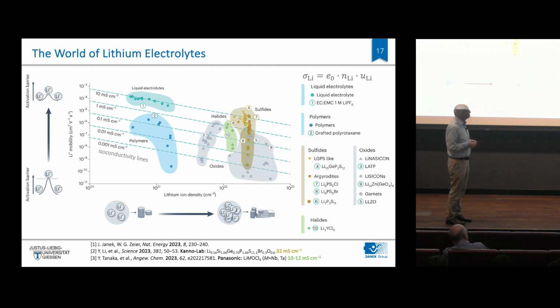We made this also a cost axis, because the more lithium ions you have, in principle, the more costly your electrolyte is. And you see here, the advantage of liquid electrolytes is they have this 10 millisiemens per centimeter at rather low charge carrier density. If you go to solid electrolytes, the sulfides can achieve the same high conductivity, but at the cost of at least an order of magnitude more ions in your material. So that's definitely one of the little drawbacks of the solid-state world. You need more lithium ions.